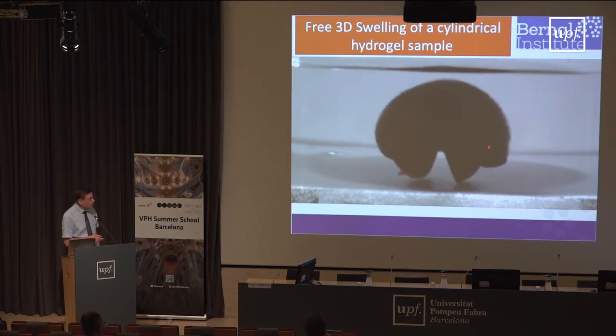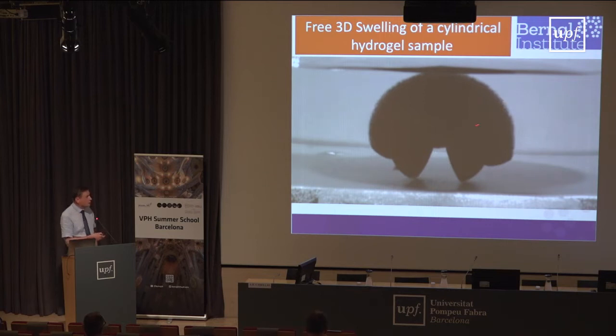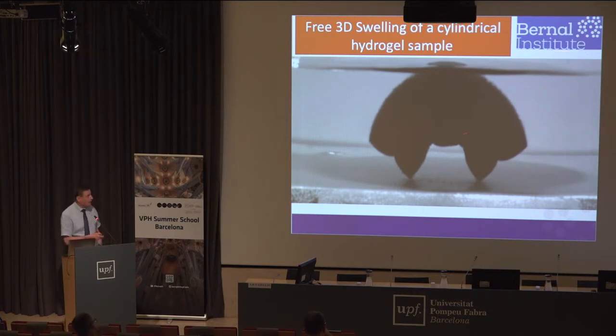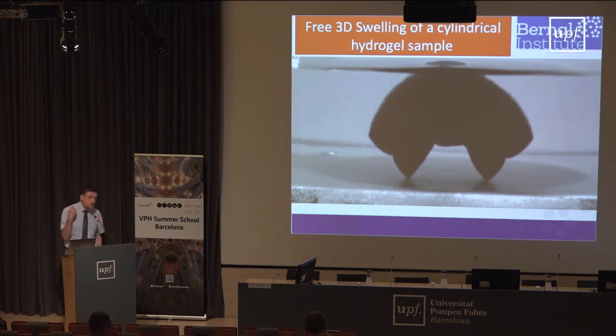So it is convex upwards in this plane, and in the plane perpendicular to the picture, it is convex downwards. So we have a kind of saddle shape, and progressively it is swelling. In the meanwhile, the ions go out of the gel, and the water goes inside, and they compete with one another. And at some point, it goes also into the center of our gel. And progressively, it then goes back into the original cylindrical shape. And going back to the cylindrical shape demonstrates that our gel is purely homogeneous. So we have a purely homogeneous gel, but still it goes into those mad shapes.